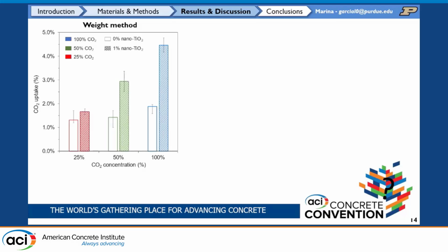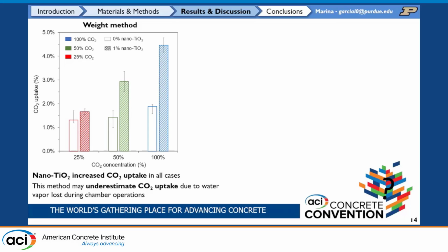So we also wanted to verify the CO2 uptake with the other 2 methods that we commented on earlier. So in terms of the weight method, we do see pretty similar results for all of them, except for one of the samples that were not nanomodified at 100% CO2 concentration, which might be due to an underestimation from not being able to account for all of the water loss during that process, which is a difficult thing to do. But we did see that in all cases, titanium dioxide nanoparticles did increase CO2 uptake.